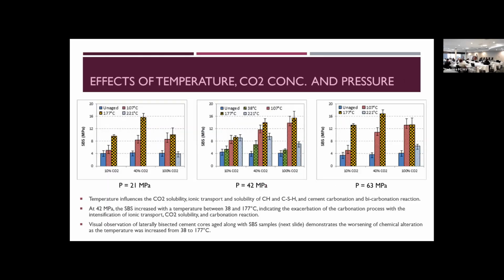With this in mind, we have noticed some very interesting facts for these samples. Keep in mind, there were 14 days in autoclave. You'll notice here that the shear bonding strength is pretty high compared to 1 day, which is typically in the range of 1 megapascal to 2 megapascal. We used temperatures of 107 degrees Celsius and 177 degrees Celsius. And, for those who are really geothermal enthusiasts, we have 221 C, a very high temperature.